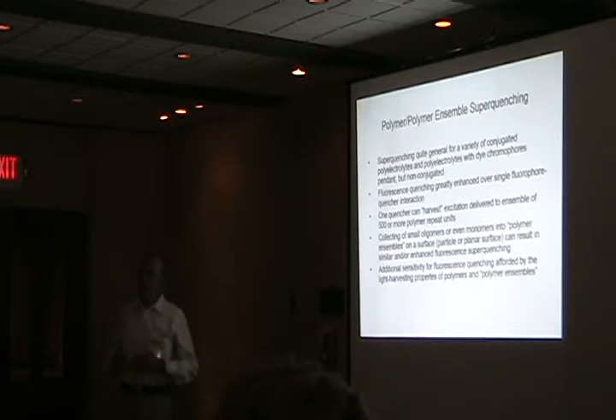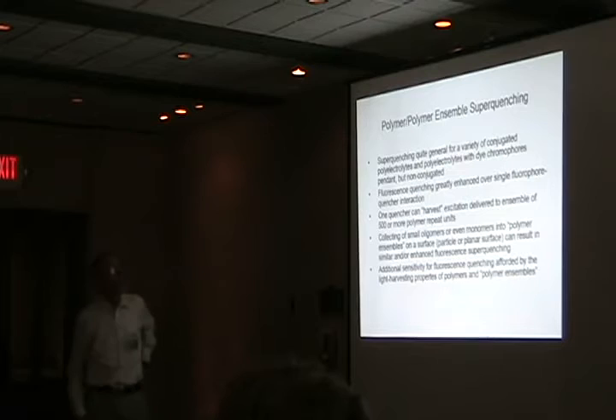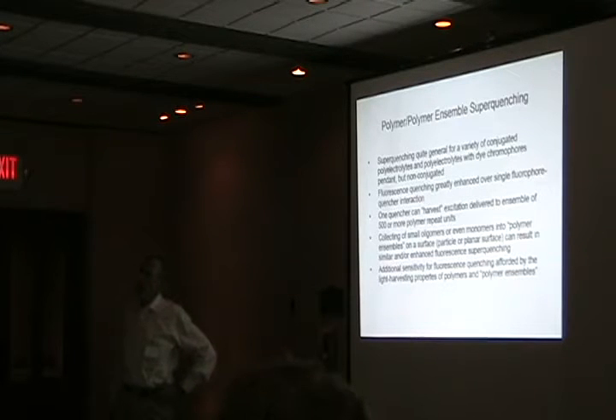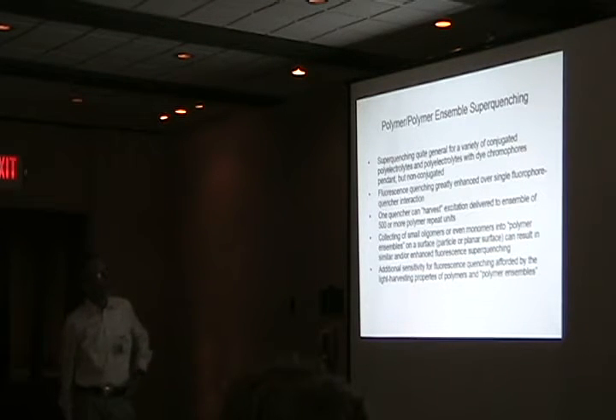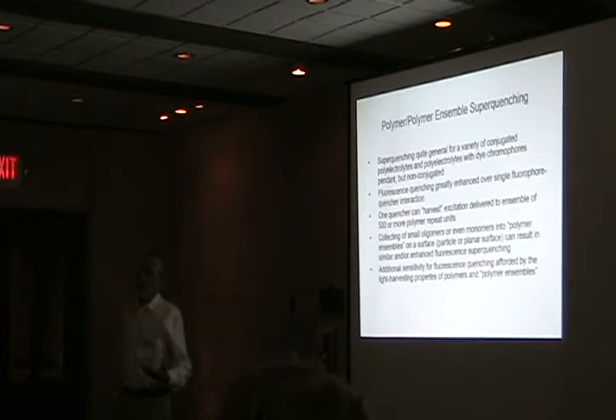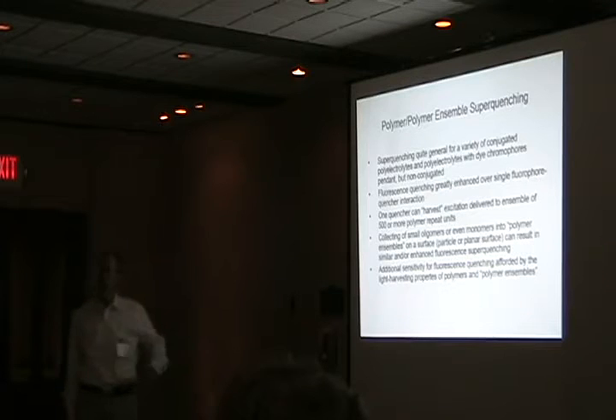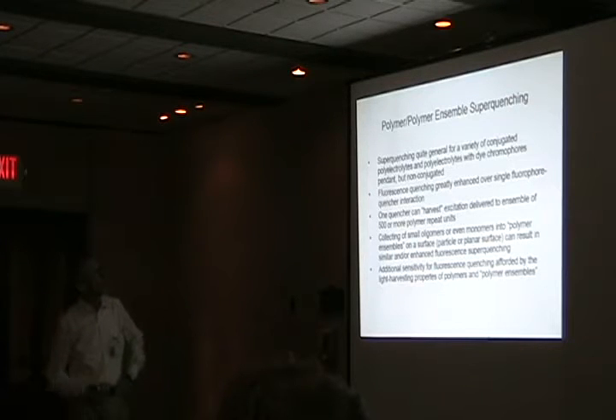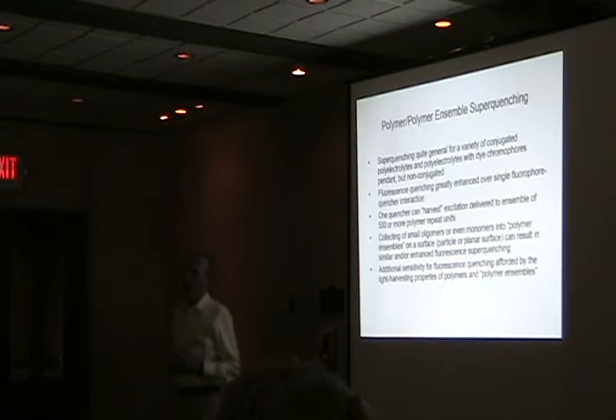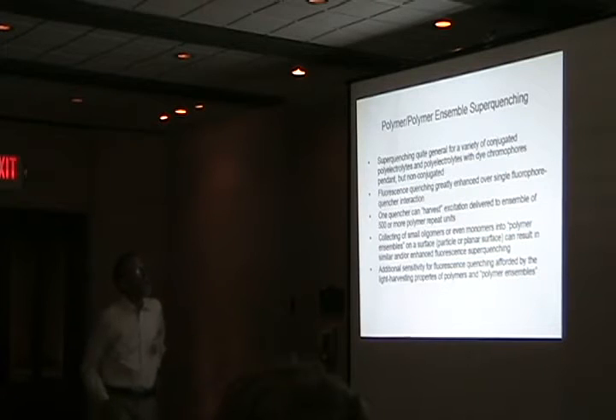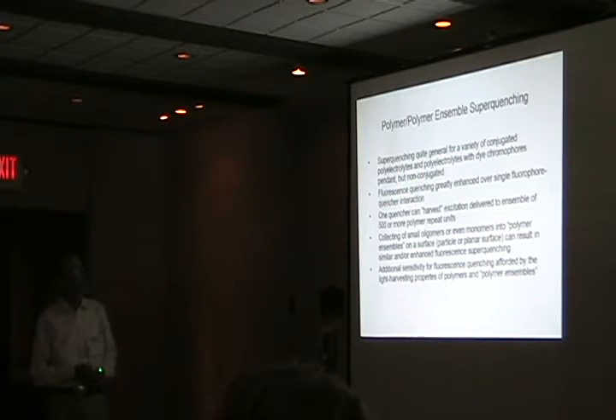And ironically, when we put these down onto supports, we adsorb onto a microsphere, we find there's very little quenching of the fluorescence. The fluorescence envelope does change, but there's very little quenching of the fluorescence, and the polymer on the microsphere support is easily quenched by the same kinds of quenchers, oppositely charged electron acceptors or energy acceptors. We also find that while there isn't much quenching for monomers or even small oligomers, when we put these monomers or small oligomers down on a surface so that they associate with each other, we get about the same level of quenching that we get with the polymer. So again, what we found is one quencher can harvest excitation delivered to an ensemble of 500 or more polymer repeat units.